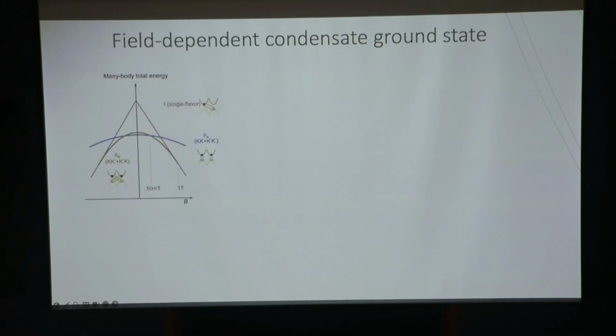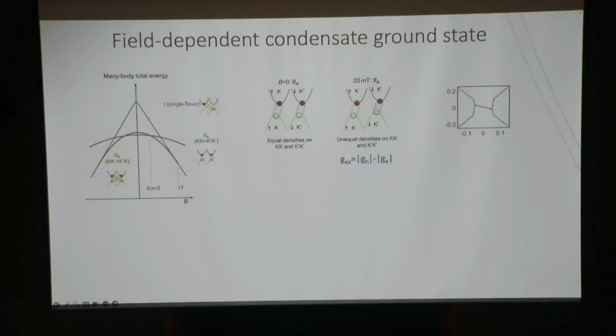OK, so when you combine that, you have 3 different types of possible condensate: intravalley 2-component, intervalley 2-component, or a single component one. At zero magnetic field, they have different energies. But then when you apply a magnetic field, they have different slopes because they have different G factors. So let's walk through this a little bit more. At zero magnetic field, these inter-valley exciton condensates are favored. So you have equal distribution of K and K prime valley excitons.